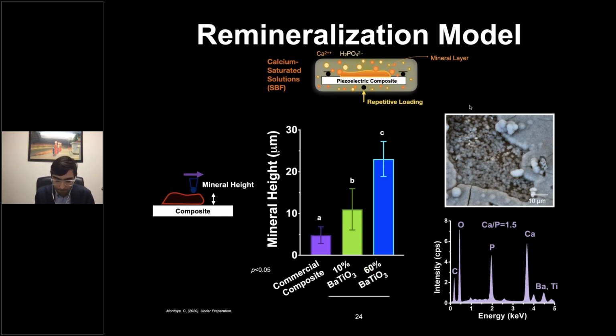As we can see, there is some inherent mineralization, which is normal because these solutions are so saturated with calcium that mineralization happens in the solution itself and precipitates. But when we introduce these charges, we begin to see an increase in mineral formation, and the more charge we have, the more mineralization we get.